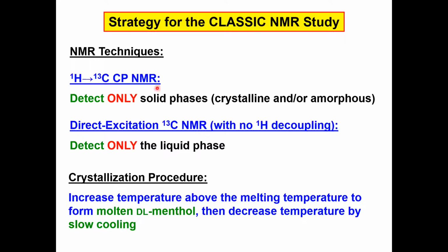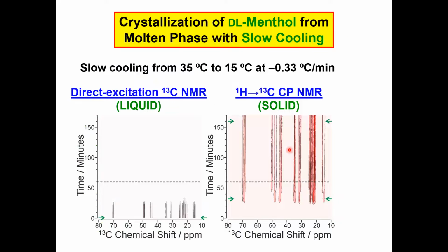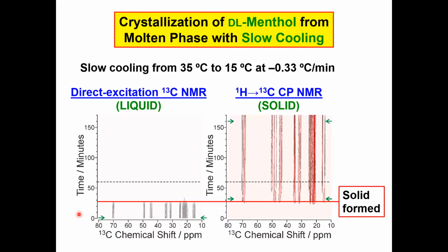Again, it's classic NMR. The solid state component is CP. The liquid state component is direct excitation with no proton decoupling. So here on the left is the liquid NMR spectra as a function of time. On the right, the solid state NMR spectra as a function of time. And we can see at the beginning, we only have a signal from the liquid state spectrum, but then at a particular point in time, we lose the signal from the liquid phase, we gain a signal from the solid phase, and therefore all of the liquid phase is basically solidified